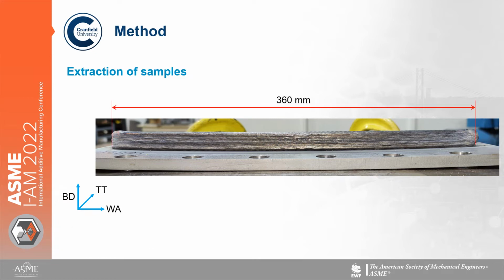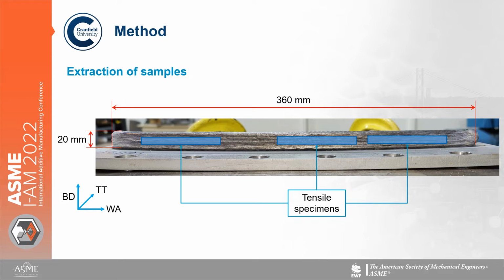So the wall was a total length of 360 millimeters and an approximate height of 20 millimeters. So we extracted 3 tensile samples per wall in those locations. And we also extracted some material for metallographic analysis.